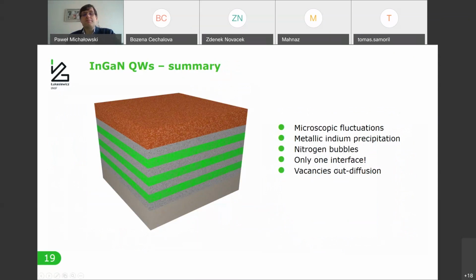And the current explanation is that during this growth, there is a huge out-diffusion of vacancies from the lower regions towards the surface, and this is causing these precipitations and decomposition of quantum wells.